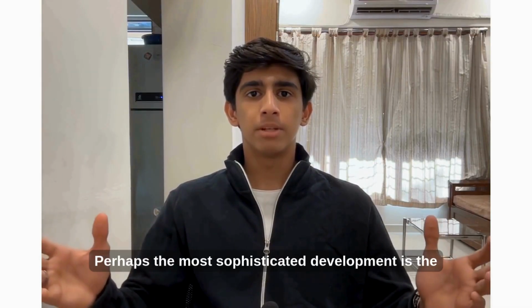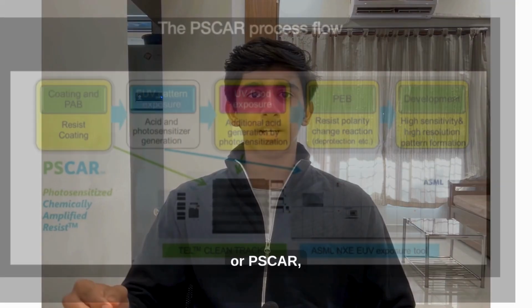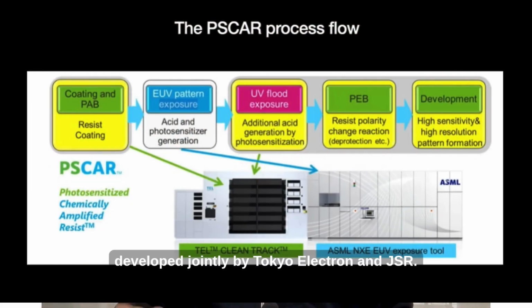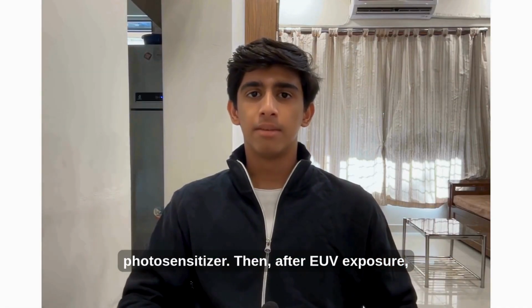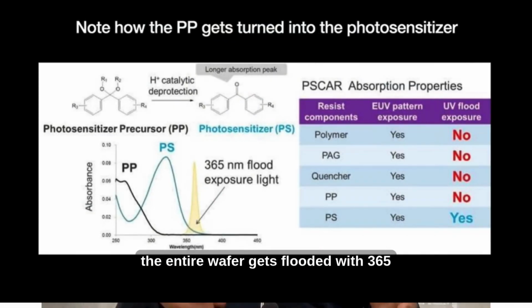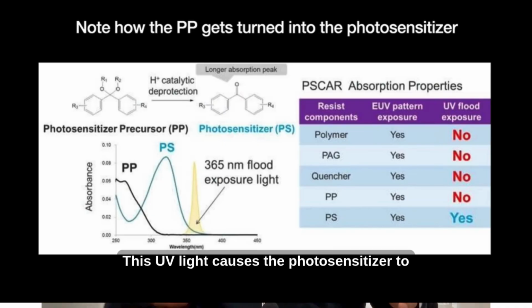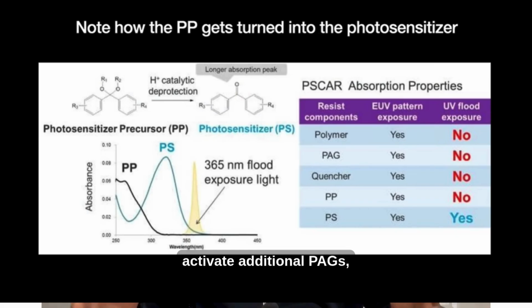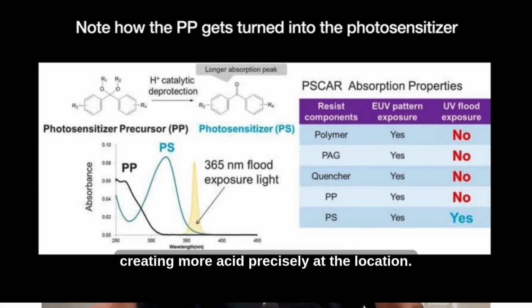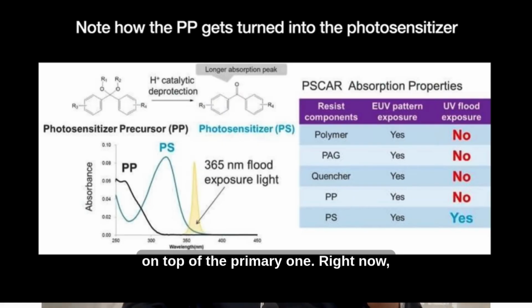Perhaps the most sophisticated development is the photosensitized chemically amplified resist, or PSCAR, developed jointly by Tokyo Electron and JSR. This is like a regular CAR, but includes an additional component called a photosensitizer precursor. Let's call it PP for short. The process also includes an extra post-exposure step. Here's how it works. When EUV light hits the PSCAR and creates the initial acid catalyst, that acid converts the PP into an active photosensitizer. Then, after EUV exposure, the entire wafer gets flooded with 365 nanometer UV light. This UV light causes the photosensitizer to activate additional PAGs, creating more acid precisely at the locations where EUV photons originally hit. It's like having a secondary amplification system on top of the primary one.